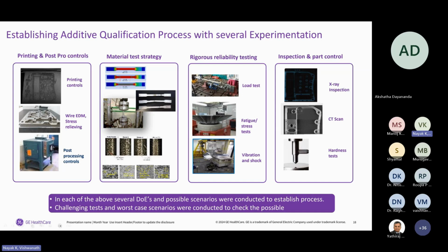But in this case, we had to do fatigue testing and stress testing over and above what we do conventionally. Conventionally, we typically don't do a fatigue or live kind of scenario with conventional sheet metal or machined components, but here we had to do it. Because this is the first time we were introducing this technology and these devices, and seeing their vulnerability, we had to do different levels of vibration and shock testing, then inspect at each stage with X-ray inspection. We also do a CT scan of this part to see if there are any anomalies which can introduce cracks over a period of time.